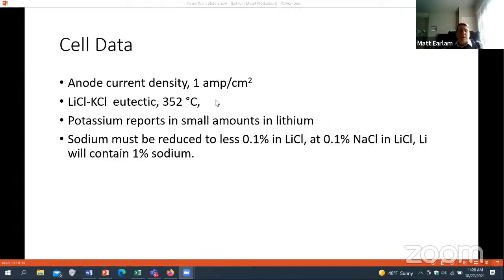So if you look at it, the anode current densities are about 1 amp per centimeter squared, typical for a molten salt system. The eutectic is 352. The sodium must be reduced to less than 1/10% in the lithium chloride, because at 1/10% sodium chloride in the brine, or the lithium chloride, it will produce a 1% sodium alloy, which is not what we want. So we really have to control this potassium and sodium. You can see that because potassium and sodium reduce at a lower decomposition voltage than lithium, it's important to get it out. Potassium is a lot closer to lithium, so you have a little less of that switchover problem.